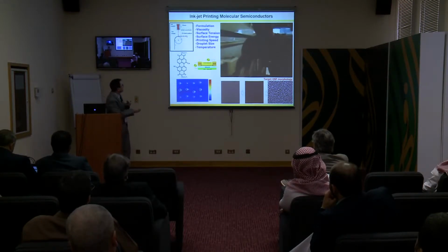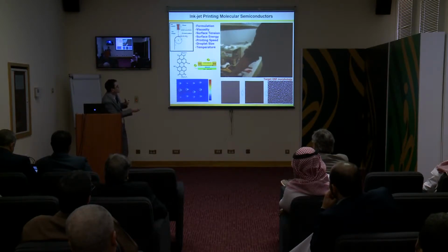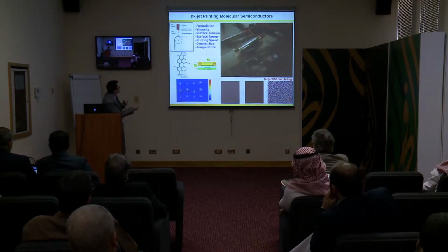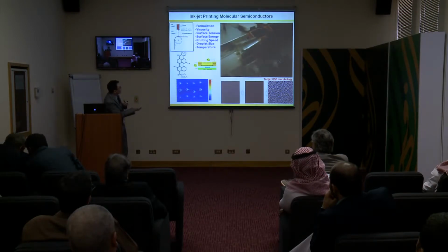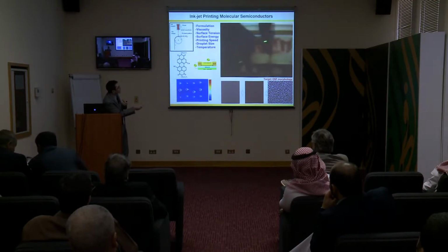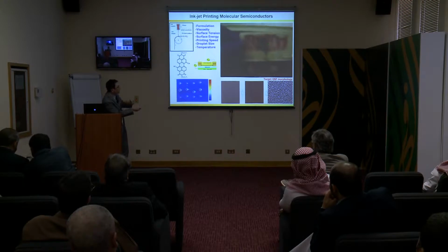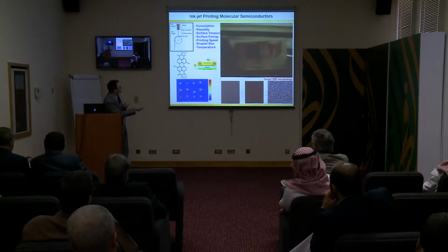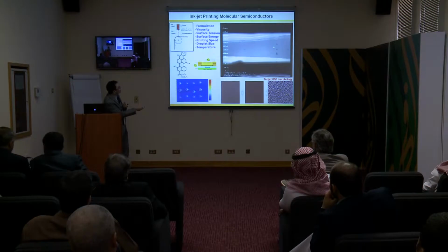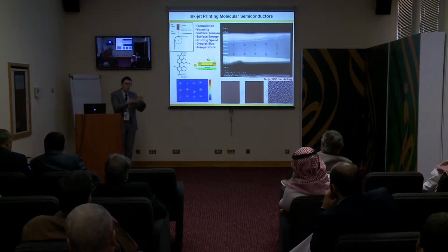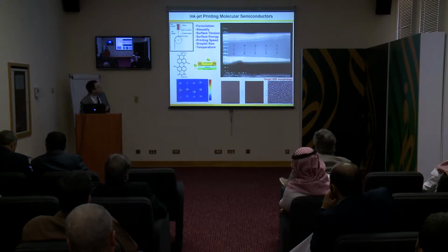The other thing we have tried to do is not only to make good conductors, but conductors which can be printable. And this is an example of a typical protocol that we do. We use plastic, metallized plastics, which we usually cut. And then we take our molecule. This is an example of cyanated perylene diimide, which we can formulate. And then this is a very simple process. This is called inkjet printing, like you print your paper, your documents, and then you have these drops which land on your substrates, and you need to worry about the topology of the drops, how they merge together. So there is a lot of work we do in this aspect.